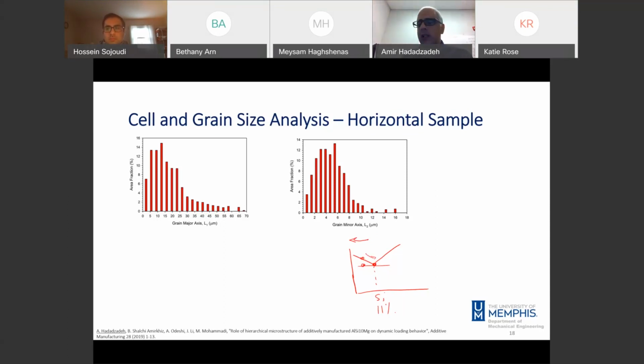That's the first point. And second, magnesium, we can add more magnesium to promote formation of Mg2Si. We didn't do that, but I guess this is a good opportunity to promote Mg2Si, because we showed that Mg2Si can play a role on the strength of the material.